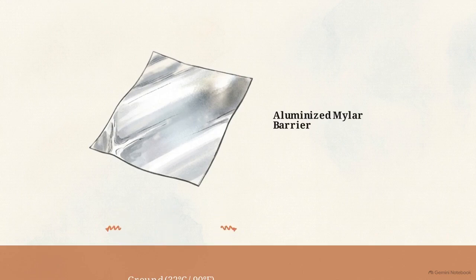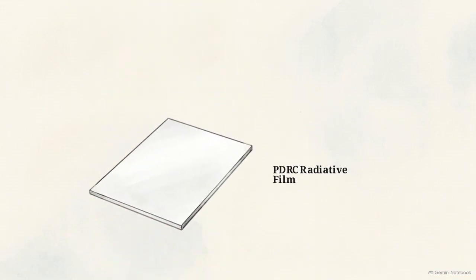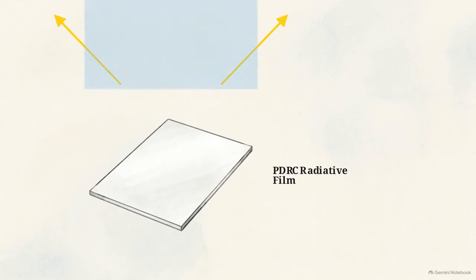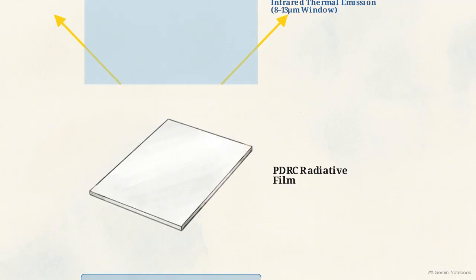Starting at the bottom, the diagram shows the mylar and the R5 XPS foam blocking the upward movement of ground heat. Soil holds a massive amount of thermal energy overnight, and these 2 layers stop it from reaching our collector. Moving to the top layer, we apply a barium sulfate-infused film. This acts as an aggressive mirror for the sun during the day, while at night it continuously emits its heat straight out into deep space through the 8 to 13 micrometer atmospheric transmission window.